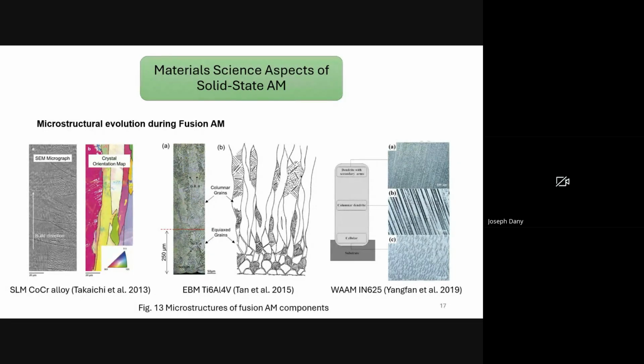The higher build temperature promotes in situ aging and phase transformation during the build, altering precipitate size and distribution. Grain morphology can be tailored by changing scan strategies, and the overall texture tends to be strong along the build direction. Parts often exhibit relatively isotropic mechanical properties when scan strategies encourage equiaxed grain formation, although columnar grain structures remain common where line scanning melting is used.